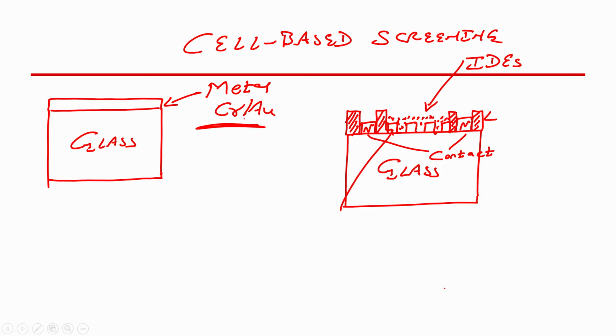Now, when I say thin and thick, it does not really change in terms of a few nanometers to microns or a few nanometers to millimeters. It is not like that. It is like 10 to 15 nanometers of chrome and 100 to 300 nanometers of gold. So, I am saying thin layer of chrome over which a thick layer of gold does not mean that it is really thick, it is still thin, but compared to chrome it is thicker.